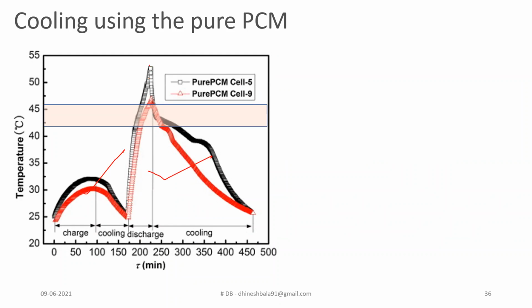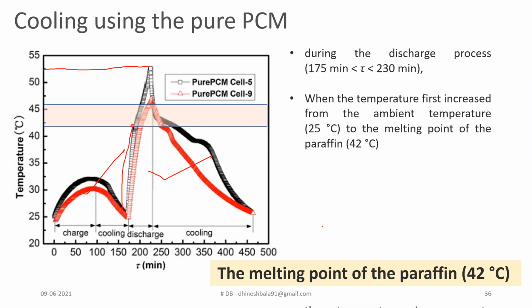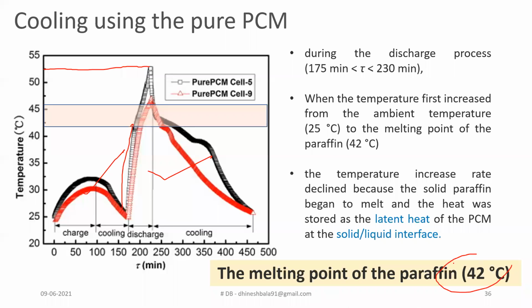In that particular case, for cell number 9, you can just see there is a drop in temperature. So it means that both for the air and the PCM material, the temperature rise would be similar till 42 degrees Celsius, because the melting point of paraffin is 42 degrees Celsius. So till 42 degrees Celsius, you won't face a very big temperature variation between natural convection and the PCM based study. But after it exceeds 42 degrees Celsius, for converting from solid to liquid phase, you need to give an additional excess amount of temperature.